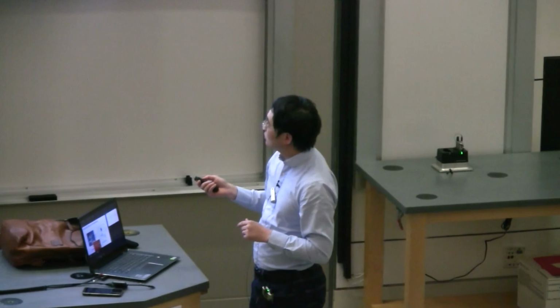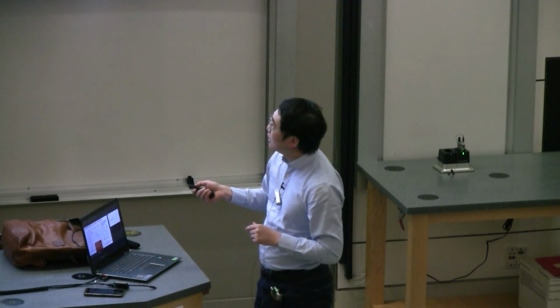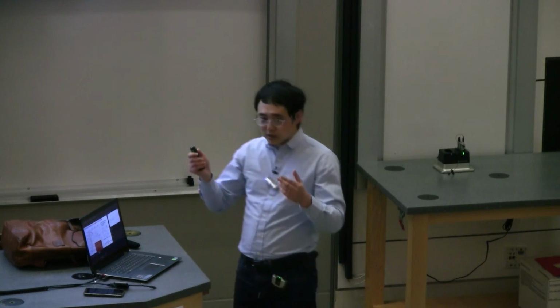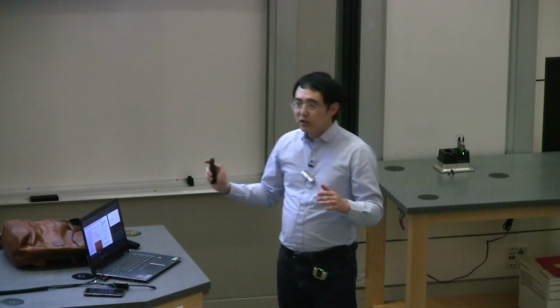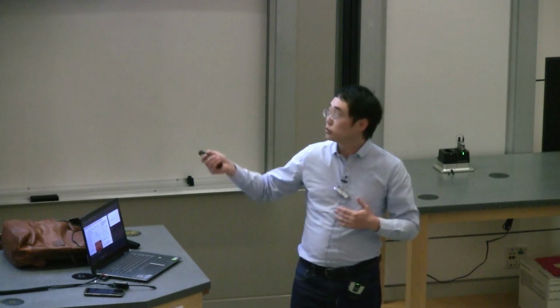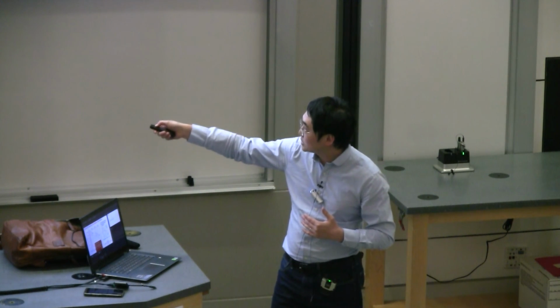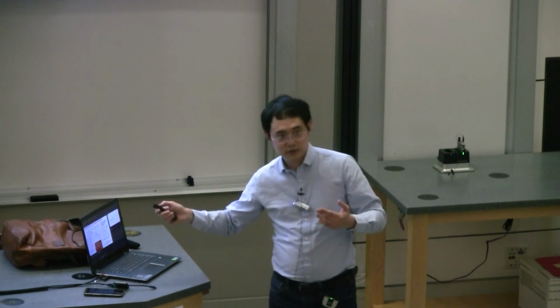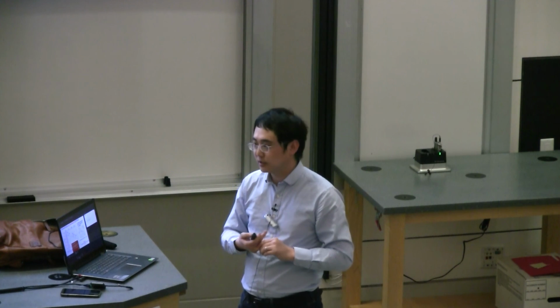Yeah. So now it's a valid question. It's on the order of a few kiloohm level. As I said, we are not reaching the lowest electronic temperature yet. Previously, we just couldn't get any superconductivity in any graphene sample. Now, we can at least get superconductivity in some of them. I think the electronic temperature is now probably 1 order of magnitude lower than before. So we should recheck this in both samples and see if the dip gets deeper or even close to 0. But is the other sample showing similar or not? Yeah, it's similar to this value. Thank you.